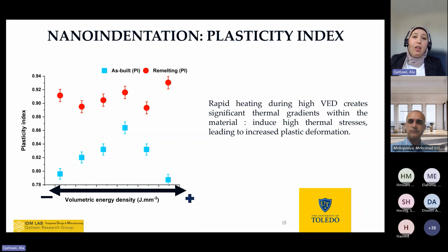And then you can see, for example, for the as-built ones, that we can reach a middle point where it's great, like the plasticity index is good, and then it has a decline. We didn't see exactly the same behavior when we do remelting. So the samples, like average samples, so these are multiple tests, not one, for the same sample, same processing parameters, can actually increase. So this also indicates a window where, if we control the remelting process, we can overcome the decrease in plasticity and then the increase in hardness of the material.